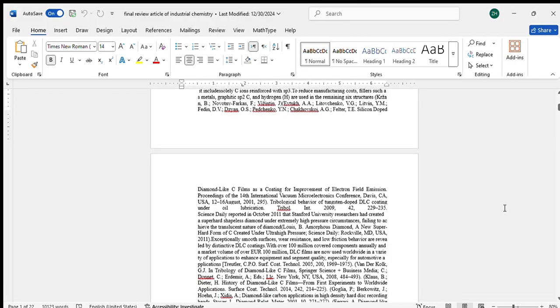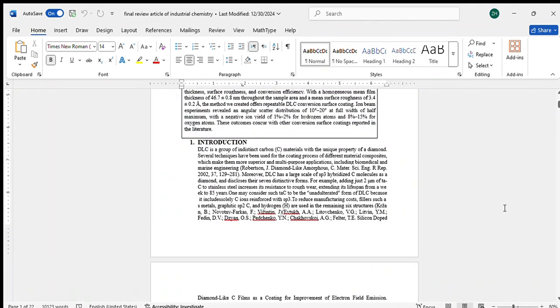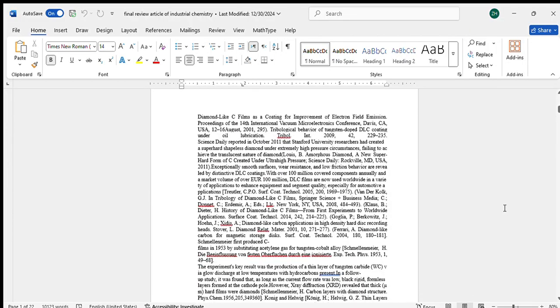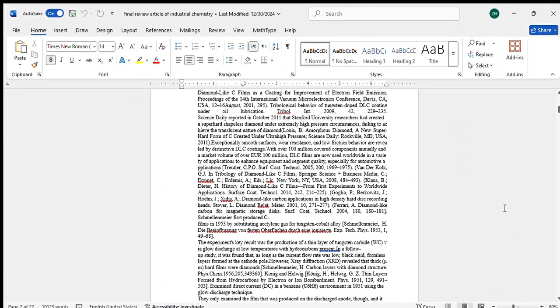There are many references which support the introduction of this article. This paper compares these two missions and emphasizes how DLC coatings play a vital role in particle detection due to their high efficiency and stability. In the study, the authors described the methods used to create ultra-smooth and ultra-thin DLC coatings. These coatings are less than 50 nanometers thick and have a surface roughness of less than 5 angstrom, which is important for the accuracy of the measurements.